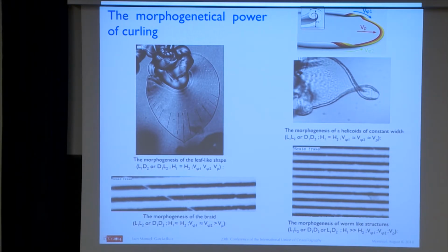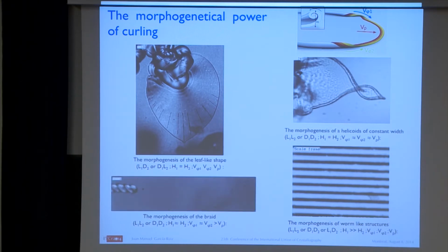Okay, so here, exactly the same, but the velocity of the counter-propagating curling is faster than the velocity of the radial growth. And then what you have is the self-curling of the 2 counter-propagating curls, okay? And this here is what we call a worm-like structure, formed when one of the curls has a radius of curvature much higher than the other one, so it curls on itself. And this is a shape.